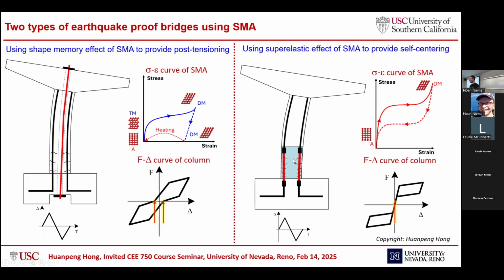We put the shape memory alloy in the plastic hinge region, in the bottom region, and when the earthquake happens, the superelastic effect of this material will also push the column back into the original position and lead to a flag-shaped force displacement curve with negligible permanent deformation.